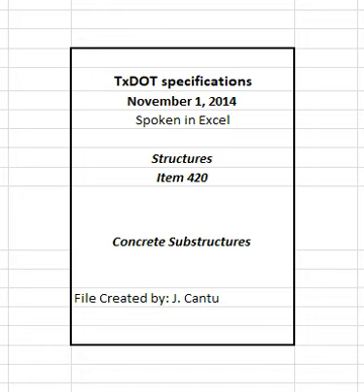Sequence successive layers or adjacent portions of concrete so they can be vibrated into a homogeneous mass with the previously placed concrete before it sets. Allow no more than 1 hour to elapse between adjacent or successive placements of concrete when revibration of the concrete is shown on the plans, except as otherwise allowed by an approved placing procedure. This time limit may be extended by 1 to 2 hours if the concrete contains at least the minimum recommended dosage of a Type B or D admixture.